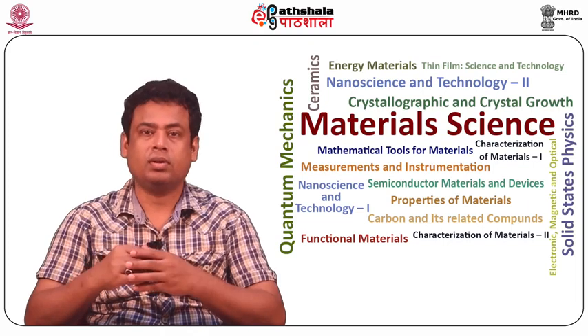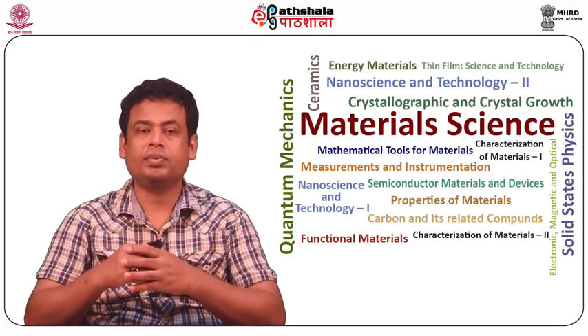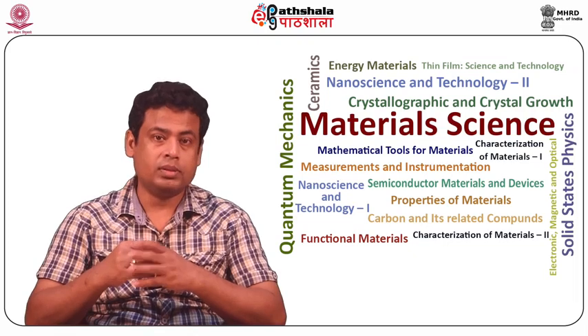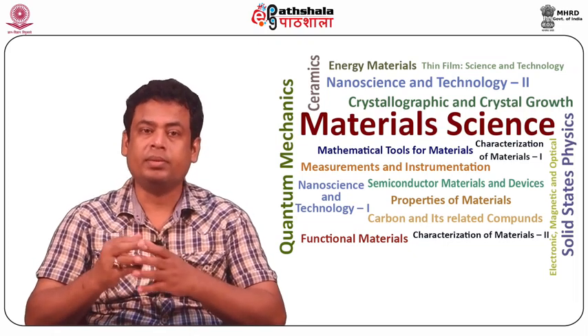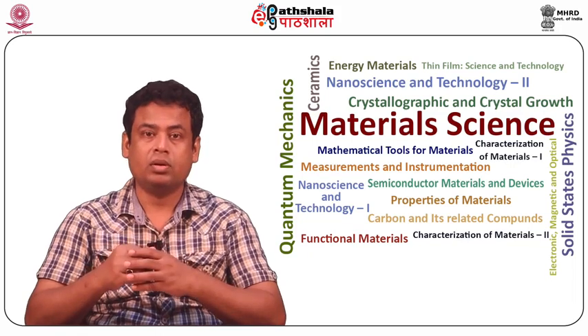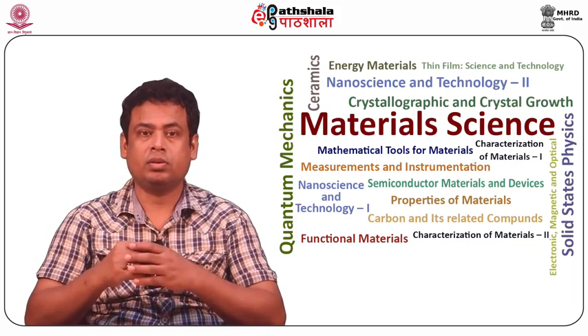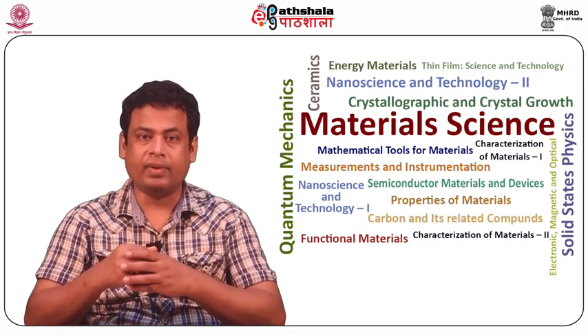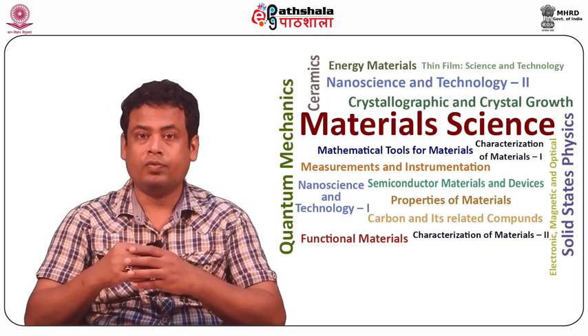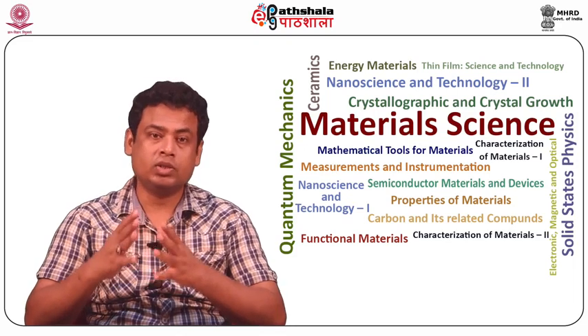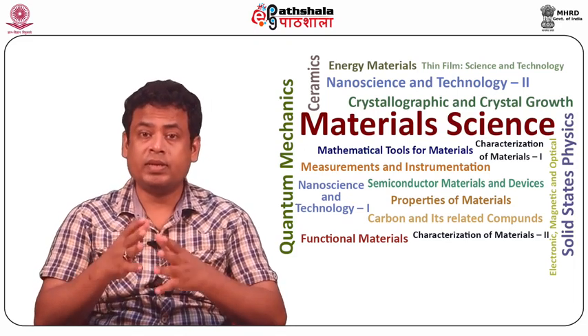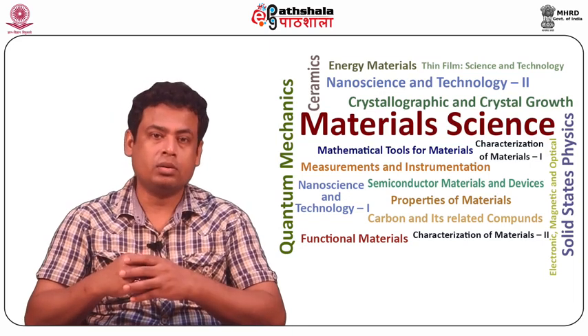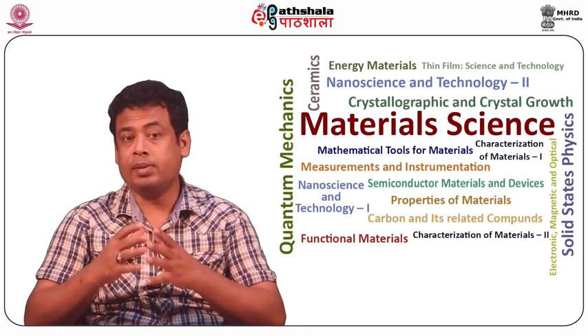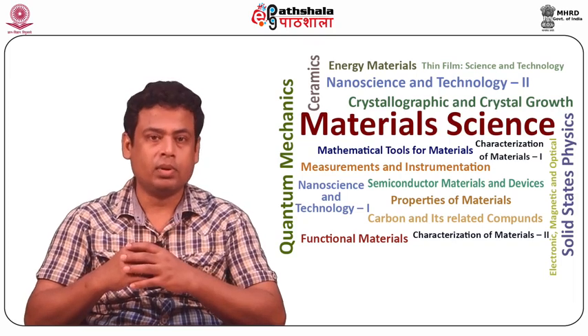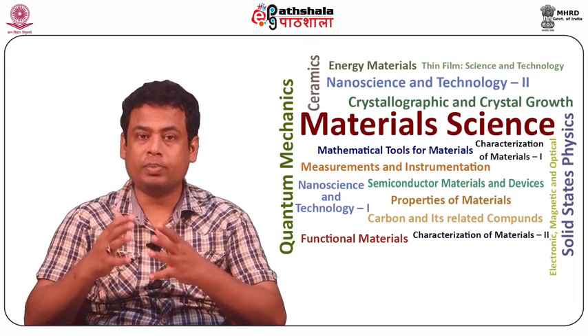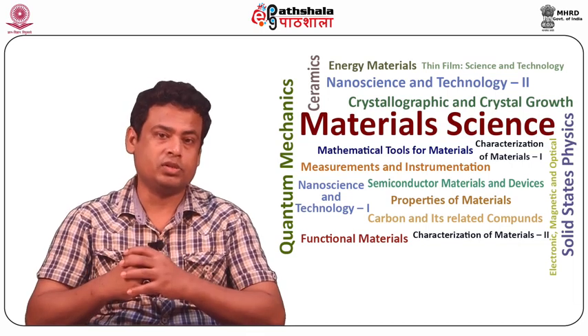These electrons have characteristic energies depending on the electronic structure of the element, and hence the characteristic energies could uniquely identify the element from which the electron is ejected. The first commercial Auger electron spectrometer became available in 1969. This is becoming one of the most popular methods of surface analysis.